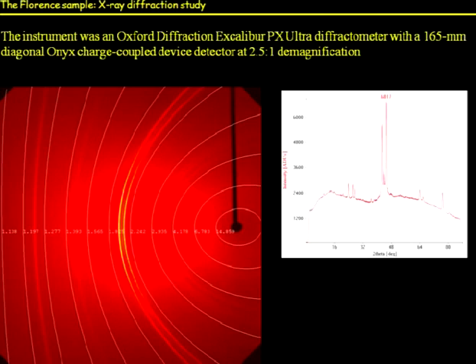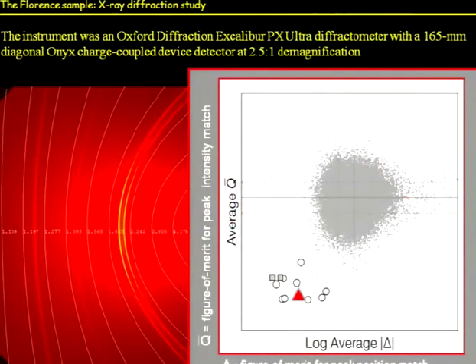And what is important is that if you plot the data for the natural crystal, this red triangle, using the two figures of merit introduced by the American guys, you can see that this natural material falls in the area of synthetic quasicrystals proved to have forbidden symmetry in the lab, and very, very far from the huge amount of 80,000 diffraction patterns of crystalline materials. So I was sure at this point to have found the first natural quasicrystal.